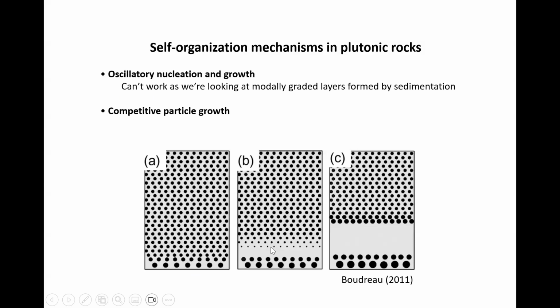And these ones here are now very, very small. So these ones here start eating up those ones. And you're going to end up with a series of layers of large particles divided by particle-free layers. Now, in order to make this work, Ostwald ripening needs long times and small grain size. So you need a mechanism in your plutonic rock where you can reduce the grain size, and it's very, very slow cooling, and it's superimposed upon an overall grain size gradient.